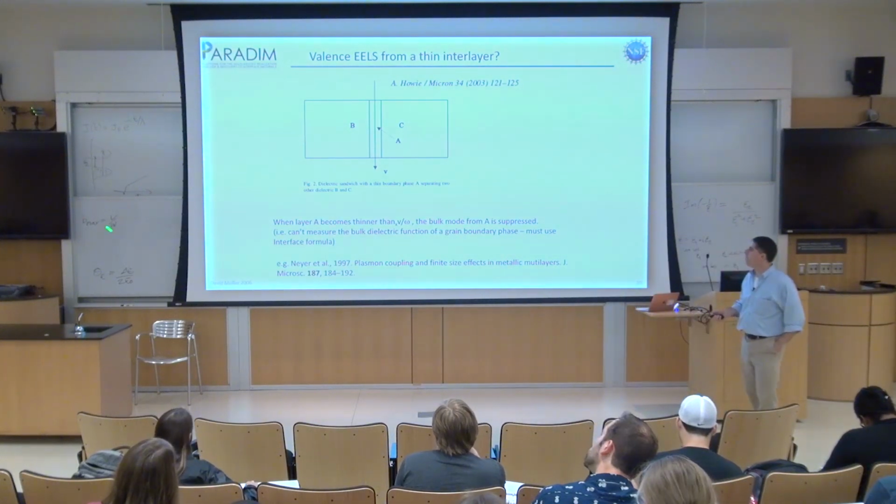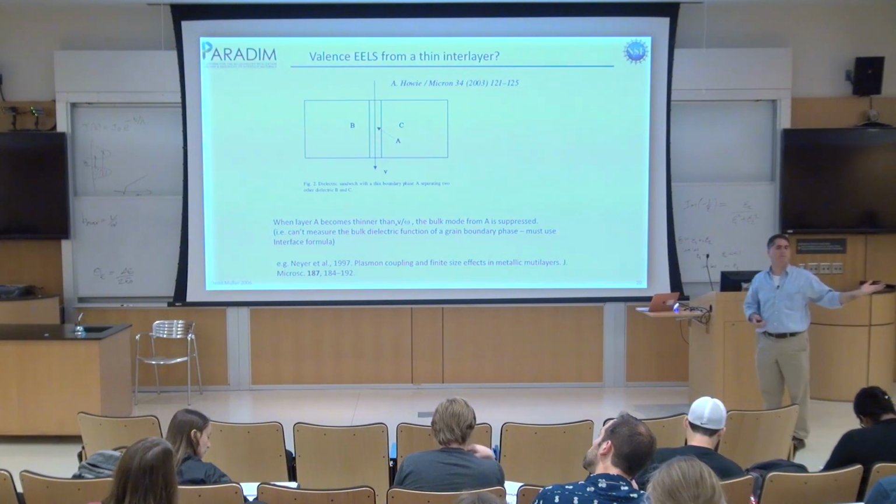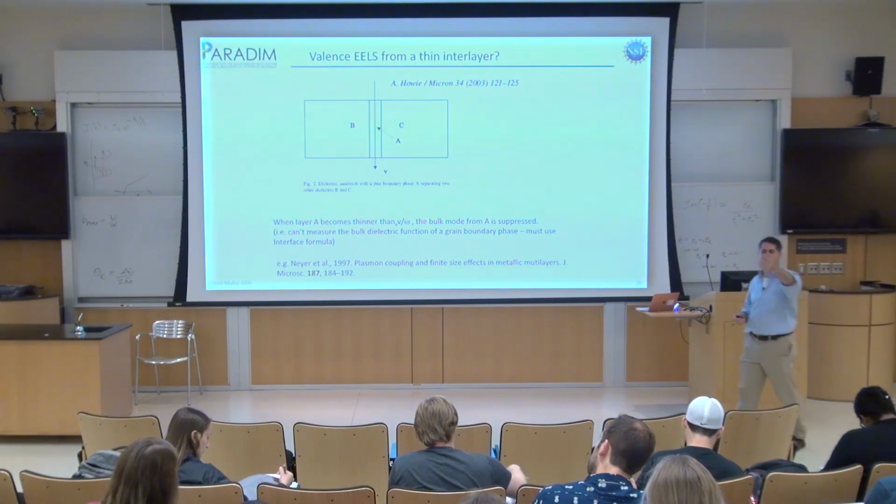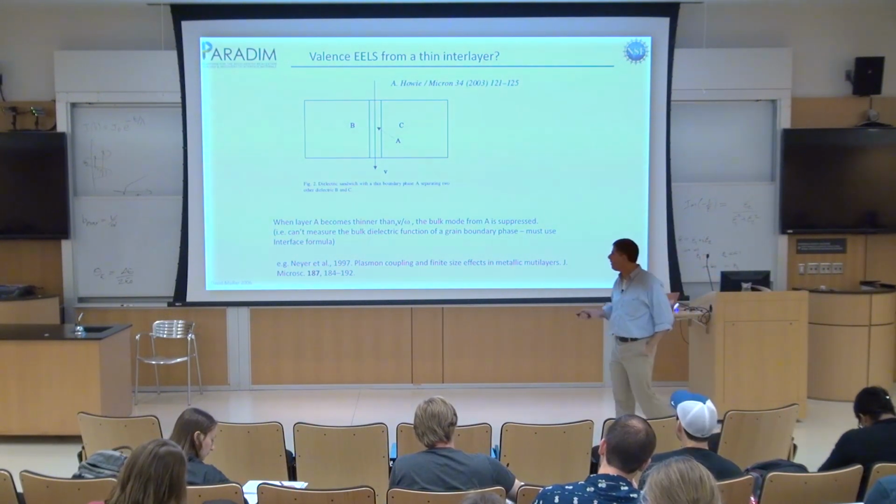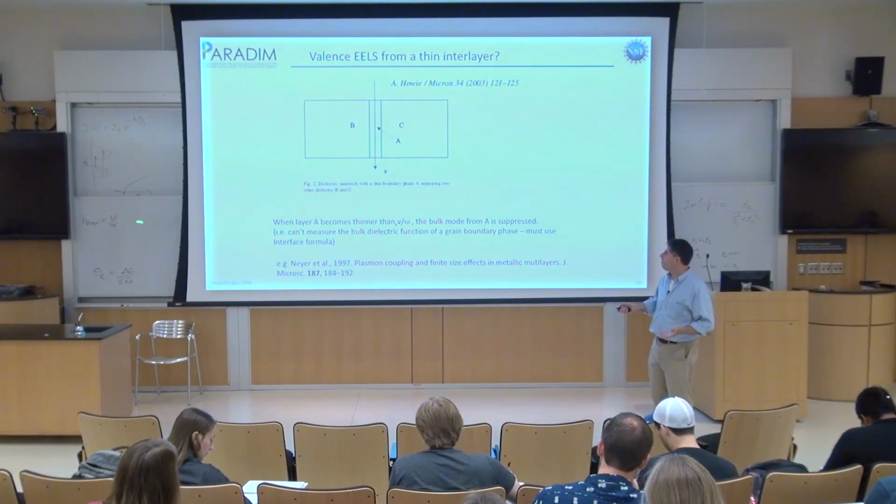And you can kind of plug these numbers in. This is still significant at like 50 volts. So if you're chasing down the magnesium edge in the material and your layer was about a nanometer thick, you may not see it.